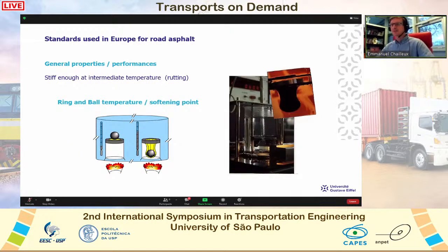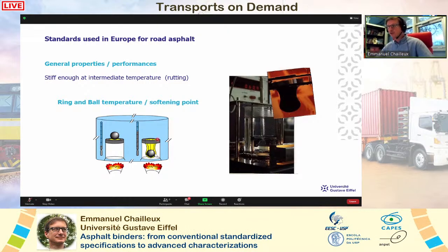Concerning the intermediate temperature, in Europe we still use the ring and ball temperature, also called the softening point, which is strongly linked with the temperature where the risk of rutting happens. I don't know if you know this type of test, but we have a ball placed on a small slice of bitumen. We heat up this system, and when the ball crosses the film of bitumen, we get the ring and ball temperature linked to the risk of rutting.